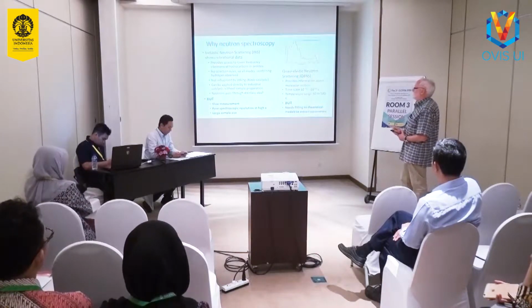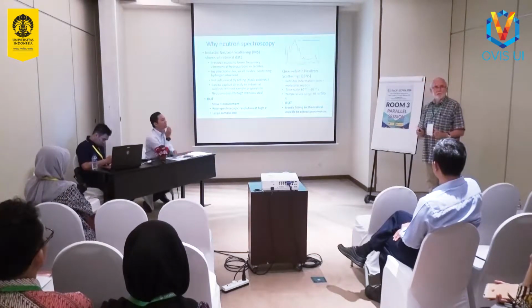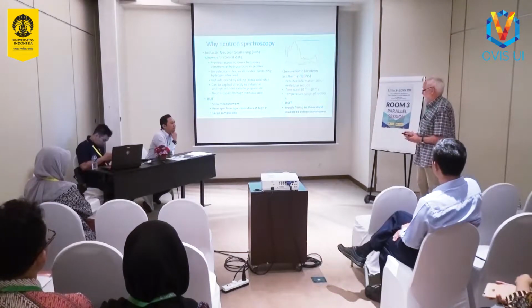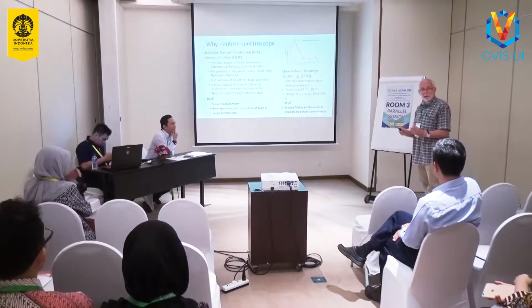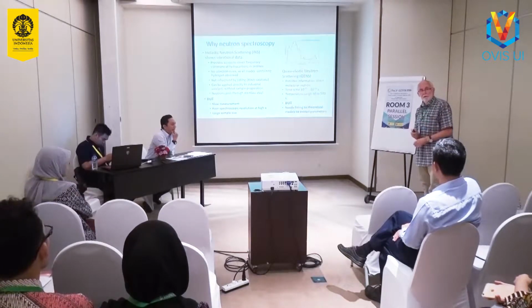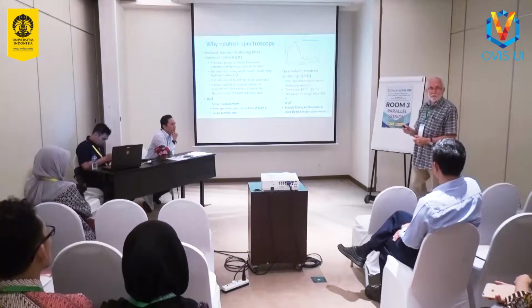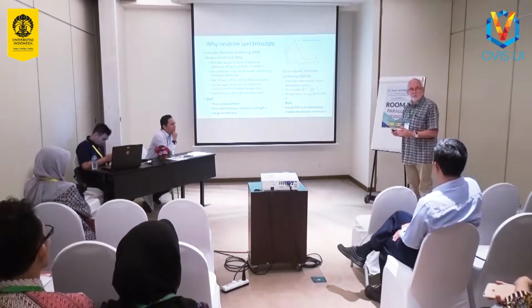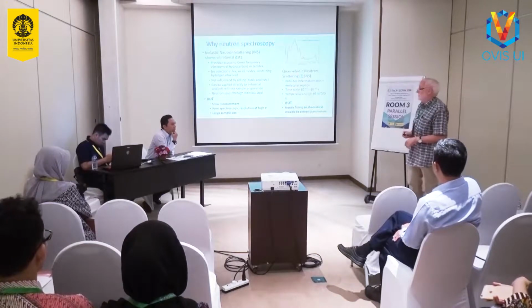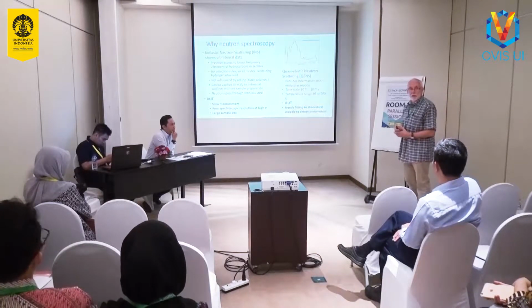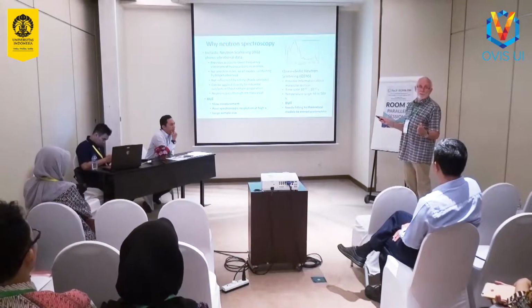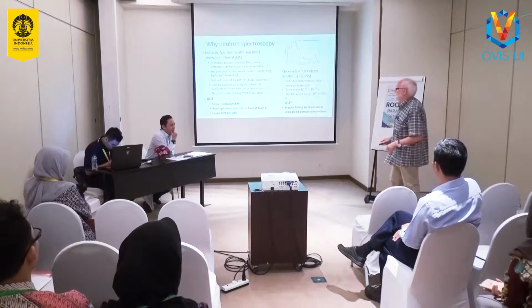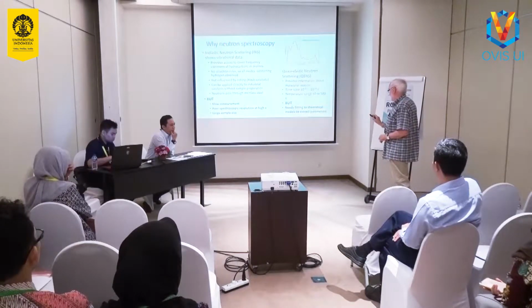Another problem we have in catalysis, if we try to look at used catalysts coming out of a reactor, particularly an industrial catalyst, like the ones we're interested in, it's often dark in color, often very black. And that's very poor for infrared spectroscopy. Very dark colored samples absorb a lot of infrared light. It's very difficult to get a good infrared spectrum from a used catalyst. Neutrons don't care whether the catalyst is new or old or anything in between. It's not influenced by the color of the catalyst.